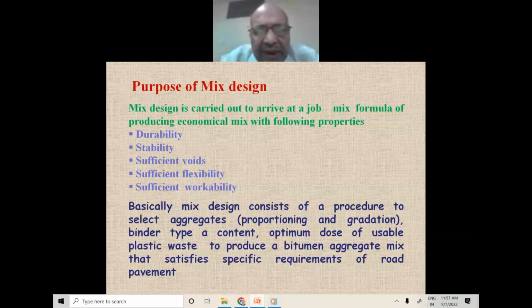The plastic modified mix must be workable at application temperature. Why is this aspect very important? Because when we mix the waste plastic in a bituminous mix, the mix is likely to become stiffer. And if the mix is too stiff, then it creates a workability problem.